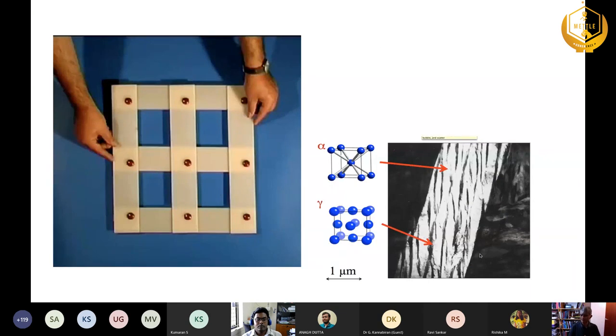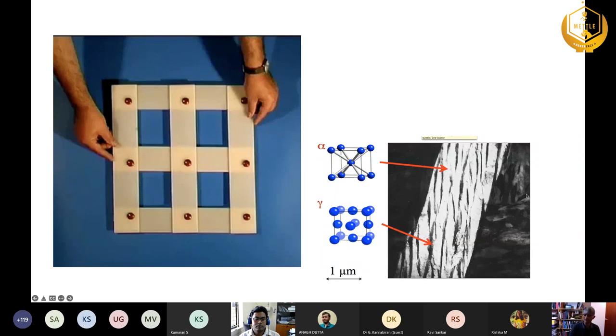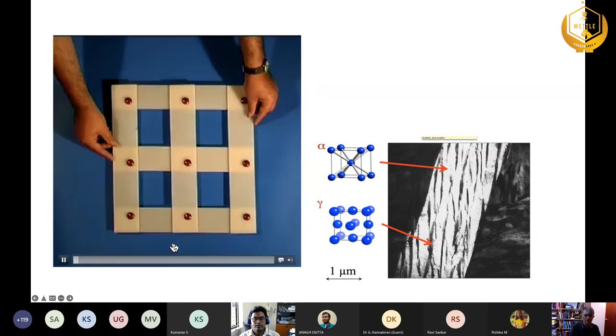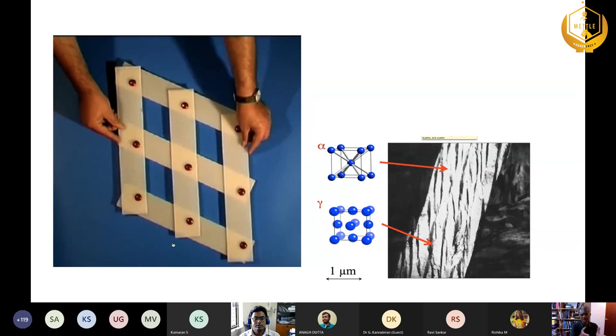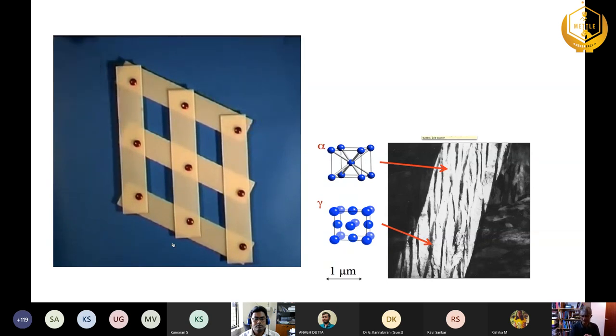Going on to the mechanism by which a transformation happens: we need to investigate how the atoms move and express their behavior quantitatively, putting it into equations and computer programs so that we can design steels rather than develop them empirically. These plates of bainite are very thin plates in three dimensions because you start with austenite and deform its crystal structure into that of ferrite — you start off with a square pattern of atoms and get a different arrangement, achieving a change in crystal structure by a physical deformation driven by the chemical free energy change. This is a shear and a volume change, and I'm going to show you a real-time observation of this shape deformation.